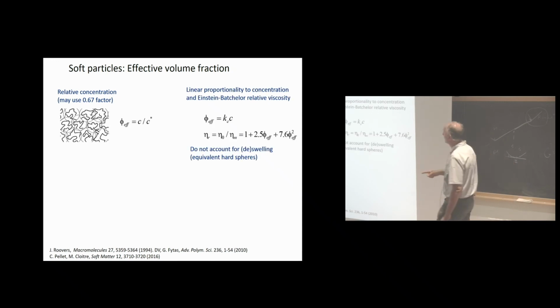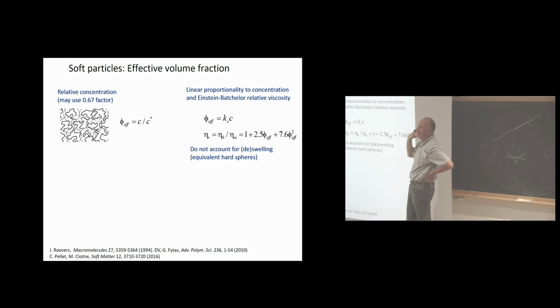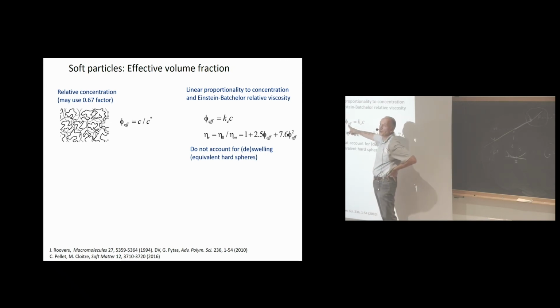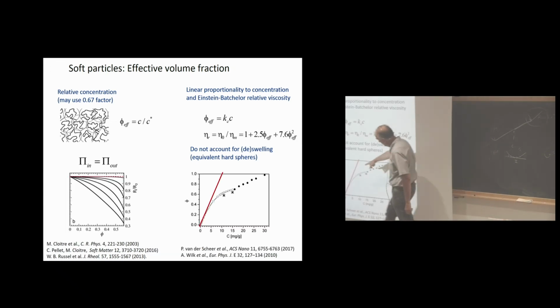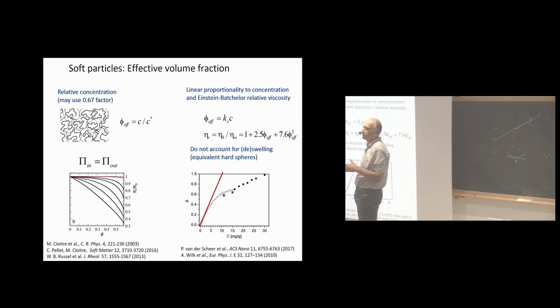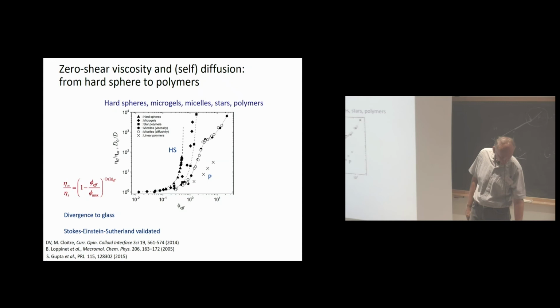Another way to do it is to use the Batchelor expression and assume that my volume fraction, which I call effective, because I define it, is linearly proportional to the mass concentration. Obviously, this is not correct, but for low concentrations, it may work. And yes, it does, right? This is my volume fraction. This is the concentration. This line is basically this linear dependence. But then, as the concentration increases, the increase of the volume fraction is smaller. Why? Because, going back to the lectures of Professor Rubinstein and Professor Grosberg, you have osmotic effects. And so when you have the contribution properly taken care of, the osmotic effects, then you see this behavior here, which I'm sorry to pass quickly, so that I make a point here.